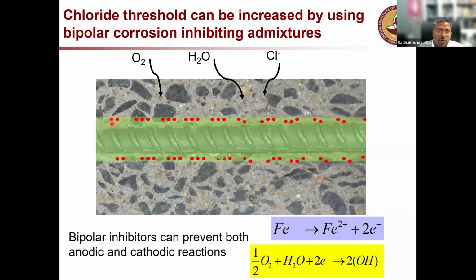One way of increasing the chloride threshold is to use something called corrosion inhibiting admixture. What we have found is this corrosion inhibiting admixture will improve the passive film which is formed on the steel surface. And what is passive film? Passive film is a very, very thin layer, the thickness could be just a few angstroms, which is formed on the steel surface and protects the steel from further corrosion. Now when you use these corrosion inhibitors, that thin layer becomes better, or it can resist more chlorides. So essentially you are increasing the chloride threshold of the steel reinforcement.